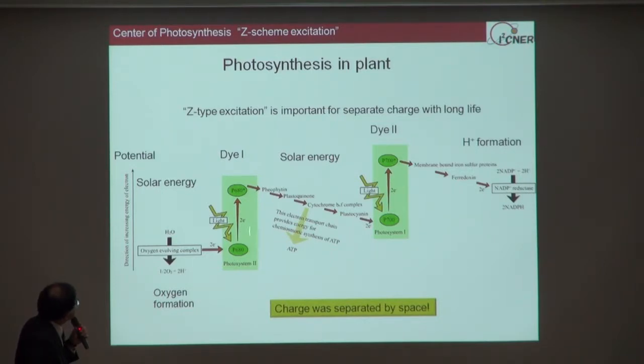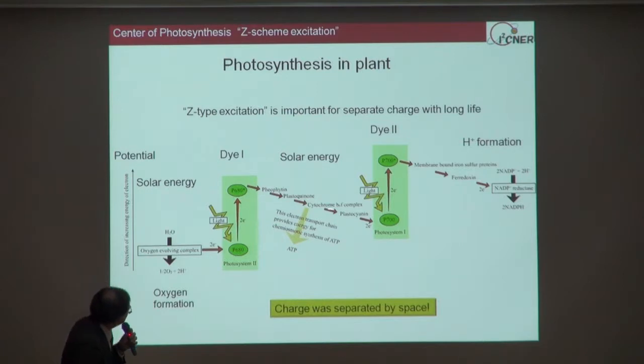And this is the procedure of photosynthesis in the plant leaf. As you can see here, they use double excitation and transfer the excited energy to the second dye by using the proton. But this process is very slow. Therefore, in our system, the excited electron is directly injected to the dye. This injection has been quite difficult up to now, but by choosing this dye and inorganic catalyst, we can successfully achieve direct injection from the semiconductor to the organic dye.